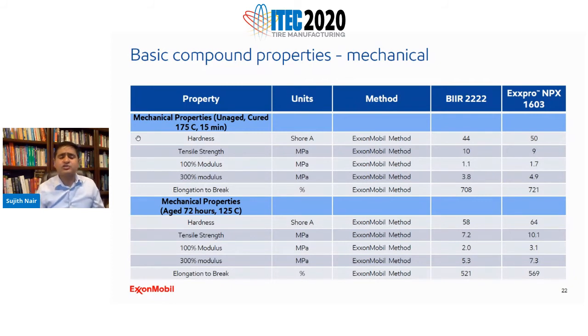One thing that distinguishes Exxpro, and we touched on this a little earlier, is the heat aging properties. As you can see, when you perform heat aging on bromobutyl, in this case we have done it for 72 hours at 125C, the strength of bromobutyl always drops, so it starts degrading. The more you age it, the more bromobutyl degrades. Whereas in the case of Exxpro, it maintains all those properties.